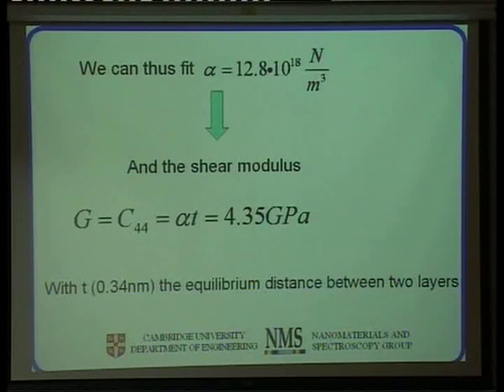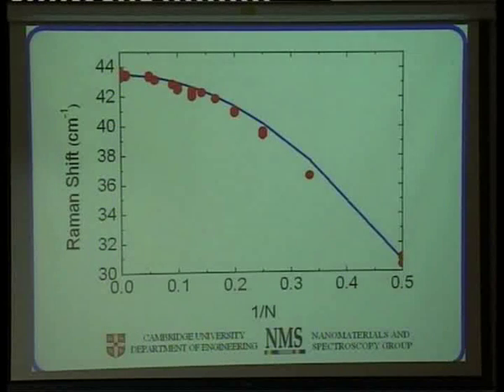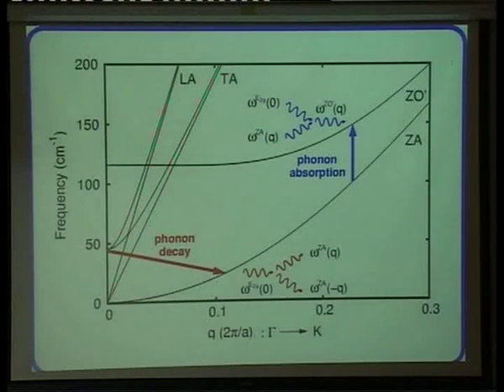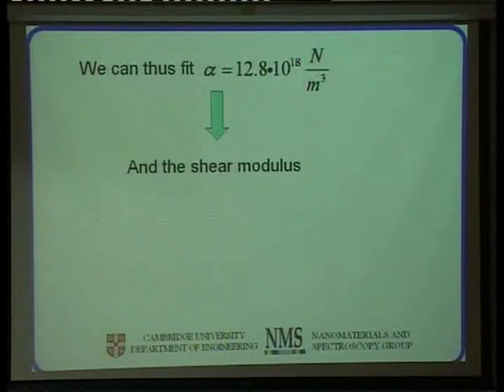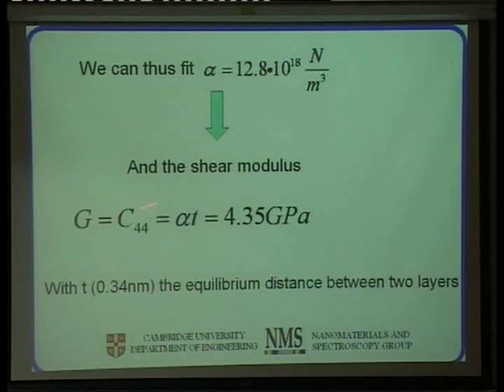Is it obvious that the interlayer coupling is the same in 2 layers as it is in 3 layers as it is in 4? Yes. To a first approximation, yes. But of course, if you want to, then you can argue that there's a slight difference between that and that, but plus or minus X% is the same. It doesn't change as a function of the number of layers, and that's the key point there. And of course, we can also measure it directly from the experiments, and if there are changes, they are very minor. So that's the first message.